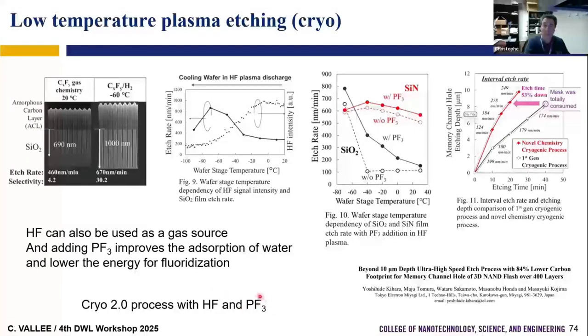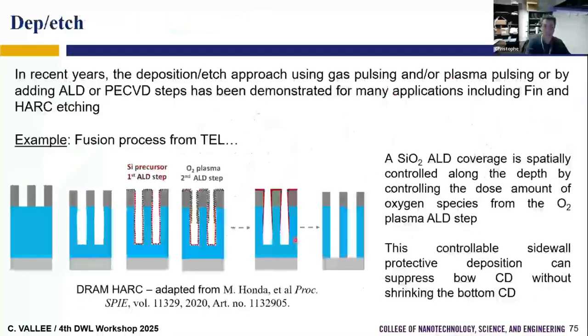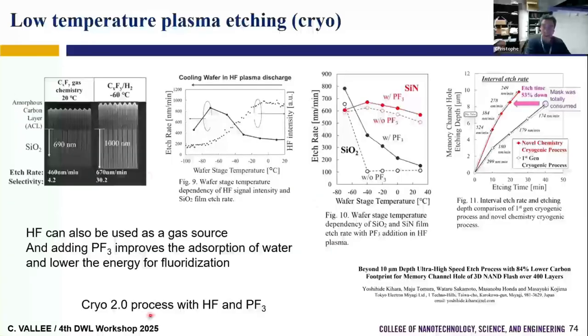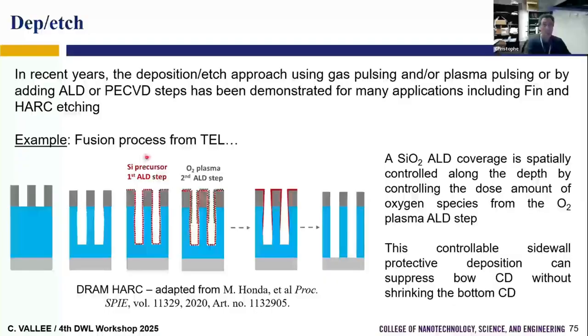And so this is, for example, the Cryo 2.0 system from LAM Research, where we have the HF and PF3 introduced for the etching, and you do the etching at minus 60 or minus 50 or minus 70 degrees Celsius. So this is where we are, and now LAM is proposing a Cryo 3.0, and probably they still have the same gas, but they don't say what they have inside. It's just maybe a slight improvement.